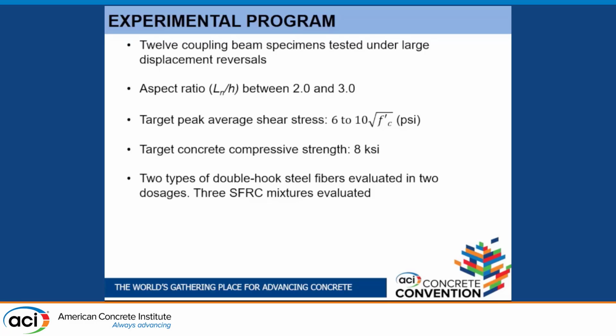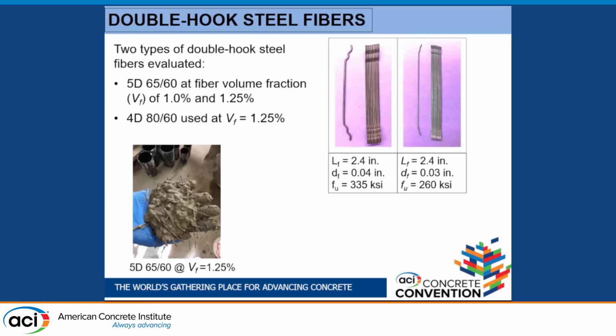We evaluated 2 types of double hook steel fibers at 2 dosages. We didn't try all combinations, so we ended up with 3 steel fiber reinforced concrete, or SFRC, mixtures that were evaluated. This shows photos of 2 of the fibers evaluated.